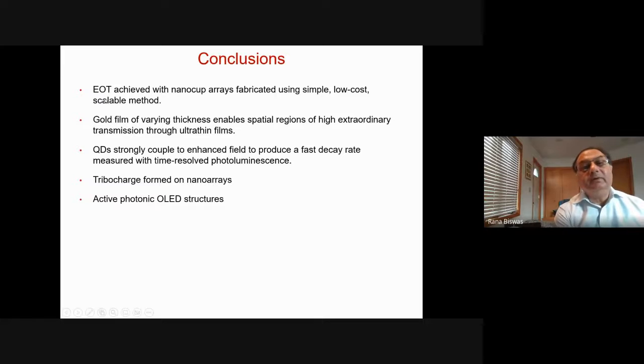And in the first part of the talk, I showed you extraordinary optical transmission achieved with nanocup arrays fabricated with a very simple, low-cost, scalable method. We used a continuous gold film. There was no lithography or etching, but the gold film had varying thickness, and this enables spatial regions of high extraordinary transmission through the ultra-thin region of the film. We then put the quantum dots within this nanostructure, and this quantum dot coupled to the enhanced electric field to produce a fast decay rate. And this was measured with time resolved luminescence and simulated with these optical simulations.